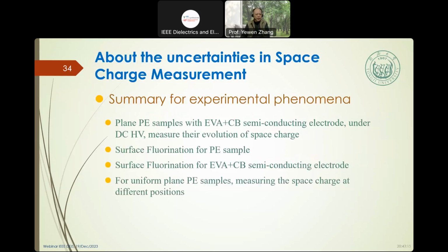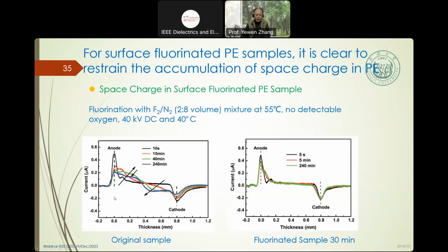So we will come quickly to the second topic, which is about the uncertainties in space charge measurement. We get some similar experimental phenomena. Planar PE with the PEA, with the EVA plus carbon black semiconductor electrode and DC high voltage measurement, shows the evolution of space charge. Then the surface fluorination for the PE and surface fluorination for the EVA plus carbon black electrode. For the uniform planar PE sample, measuring space charge at a different position, we can get some experimental phenomena.